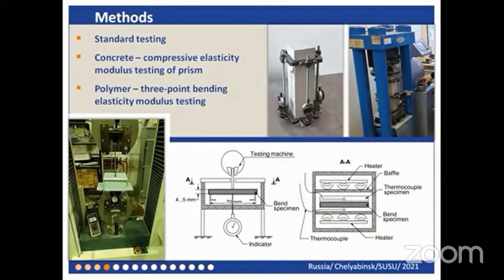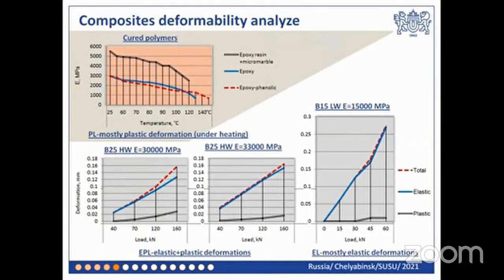3-point bending tests of polymer samples were carried out on a continuous Olsen testing machine in a specially made small-sized chamber which provides heating. The examples of short-term elastic and plastic deformation testing under compression and bending are shown in the presentation. Polymer composites have definitely elastic properties in normal conditions, but with heating, the polymer structure becomes viscoelastic. The slight deformation surfaces are appearing. Polymer structure can be presented as domains or macromolecules severed by ITZ.